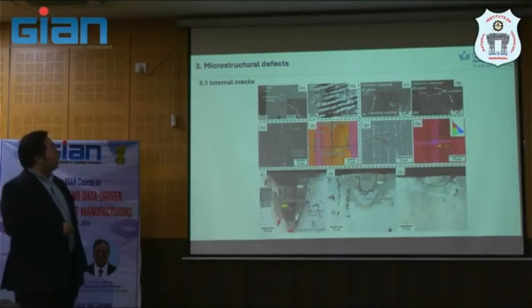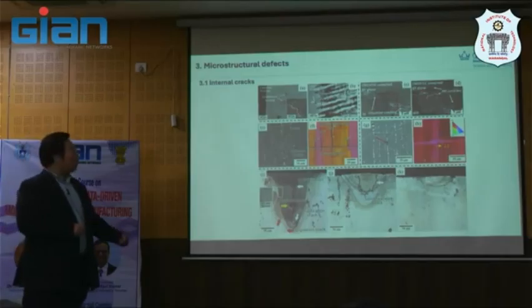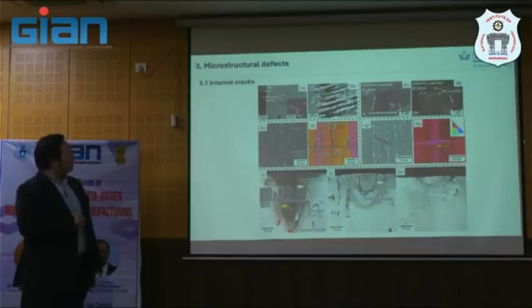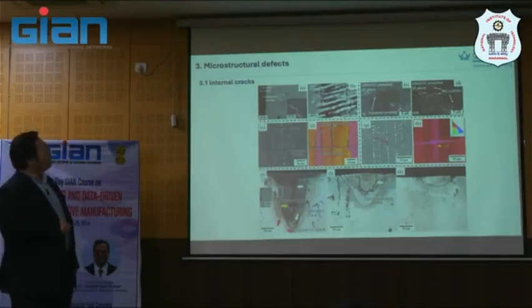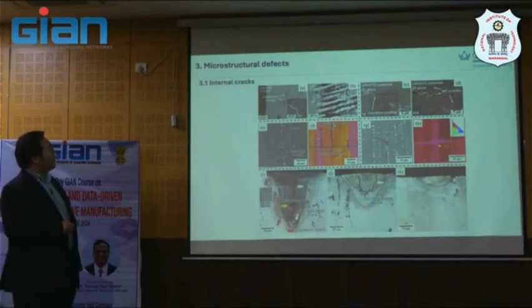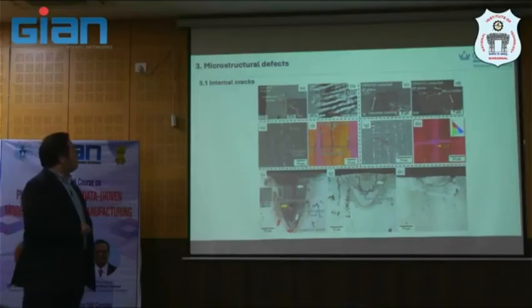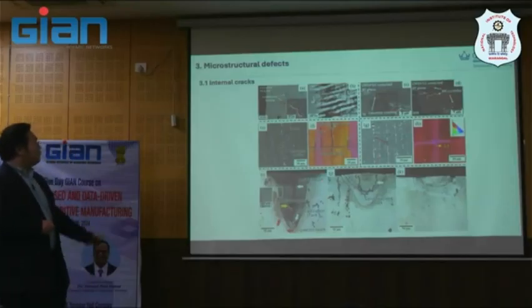Be aware that this scale is just half a micron. So it's so thin that you probably would not notice it as a dendrite. It's only primary arms that are actually taking place here. So you see evidence at the crack feature here, and then you zoom in using very high resolution SEM, you will see this kind of dendritic structure here. But it's not just solidification cracking. As I said, there will be other types like brittleness cracking, and then carbide cracking as well. So this is something we want to talk about in more detail.